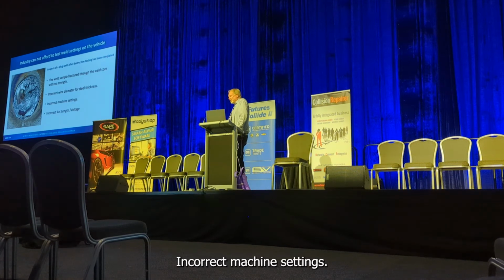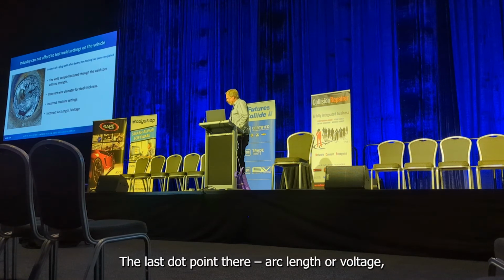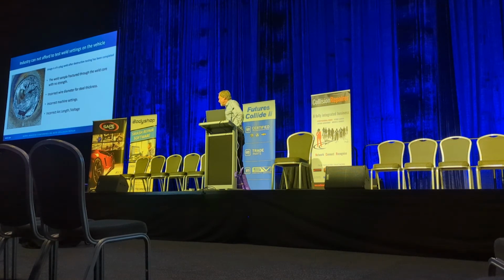Incorrect machine settings. If you don't have your amps or your voltage high enough, it won't melt the filler wire correctly, and it will not burn into the thicker steel. With the tighter metallurgical structure of the steel, you need the heat to burn into the base plate. The last dot point there, arc length or voltage.